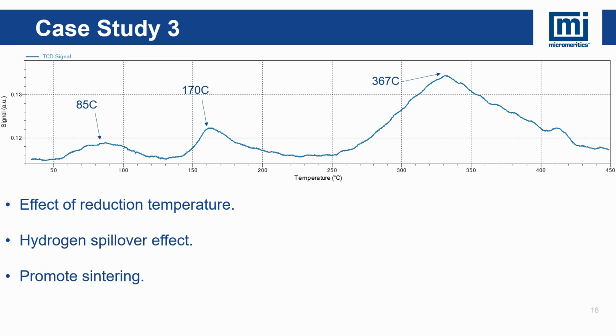In case study 3, we look into the implications of reduction temperature on metal dispersion, the hydrogen spillover effect, and the promotion of sintering. In the first stage, we perform a temperature-programmed reduction (TPR) on platinum-alumina to obtain a temperature profile. During this, we observed 3 peaks at 85 Celsius, 170, and 367 Celsius. Next, we conducted multiple dynamic chemisorption experiments to compare the dispersion results. Additionally, we took one step further to promote sintering by reducing the sample beyond the calcination temperature.